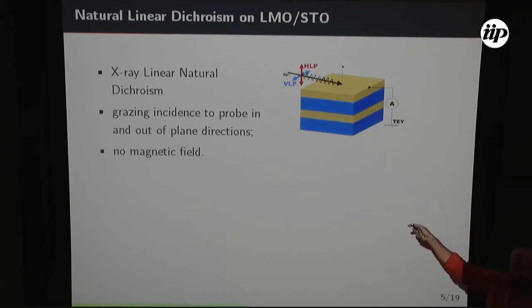I'm going to show you the results for the two extremes of the samples. So here, notice the following. When you have a vertical linear polarization, again, it's vertical here because the thing is rotated by 90 degrees. But vertical polarization, in our case, probes mostly, the electric field of this polarization is probing the electrons that are in the plane of the sample. On the contrary, the other polarization, to a great extent, has its main projection along the normal to the surface.